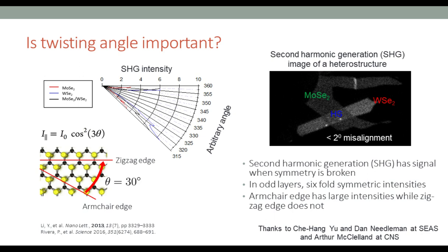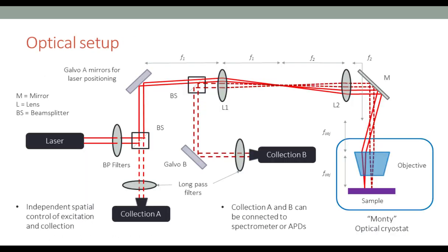Now I'll move on to the optical setup that we use. We use a 4F confocal microscope with a Montana cryostat. We have 2 lenses and steering mirrors, galvo mirrors, that allow us to put our excitation position anywhere on our sample, and it will be focused to a diffraction limited spot. Most of our experiments are exciting with 660 nanometers, so we're looking at around 660 nanometers to 1 micron spot size.